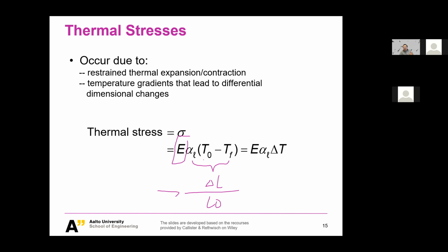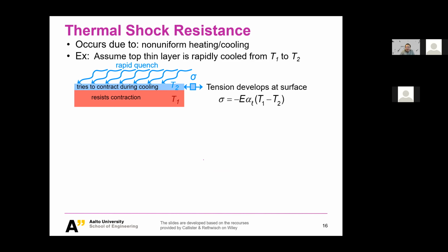For example, when we talk about steel, you remember when the temperature is low, we could have the ductile-brittle transition. And when we have the ductile-brittle transition, you really could have fracture in the elastic regime that could be led by thermal stresses. So this is just talking. Now I would like to give you one example about this thermal stress-led failure, the so-called thermal shock resistance.